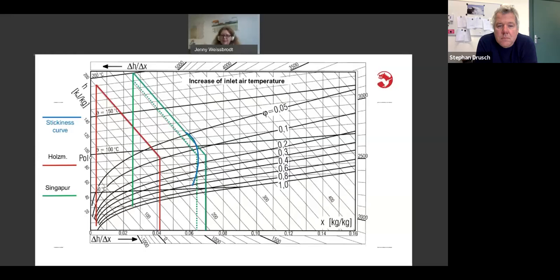So what happens if we now increase the inlet air temperature? Your drying air is still the same. It has the same moisture content. So even if you heat it up, it still has the same moisture content. And if you now do your drying, you just end up on the right-hand side of your stickiness curve, where you don't have any drying. Yeah, you have a plastic mass within your drying chamber, and you have to clean up. So maybe this is the wrong direction.